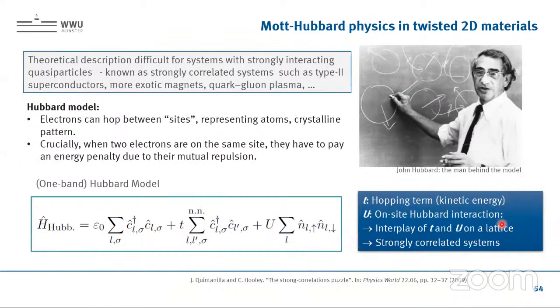So on-site potential means if there's already a state at one site, you need to pay an energy penalty to bring in another state. And it must have opposite spin, for instance. And the interplay of the hopping term and the on-site term is very crucial to define the properties. So in general, you would need a rather low kinetic energy and high on-site potential. A flat band is exactly where we have low kinetic energy, but high density of states. And we said these correlated phenomena can occur.